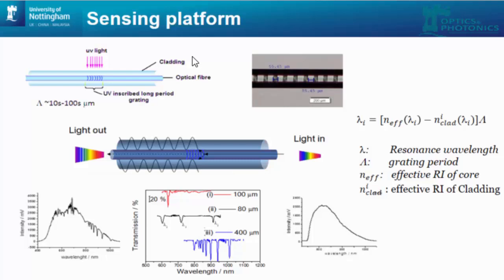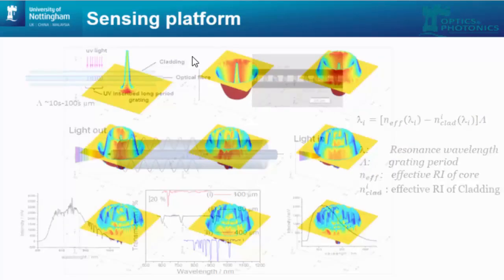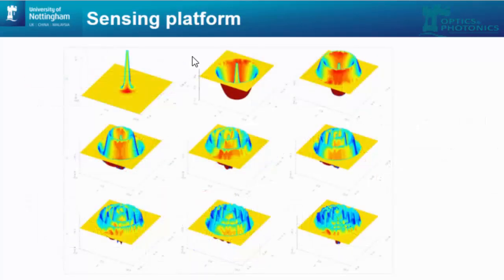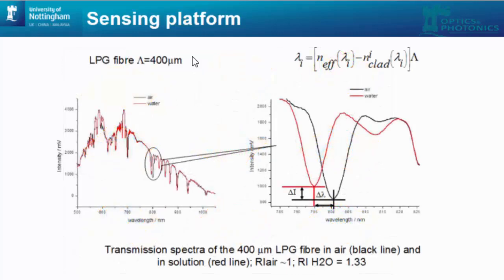So what it does to the transmission spectrum: if you put a broad transmission spectrum into an optical fiber that has a long period grating, at the end of it you will have attenuation bands, and the position of these attenuation bands depends on the grating period, so the distance between two adjacent planes, the effective refractive index of the core mode, and the effective refractive indices of the cladding modes. To illustrate this, in the fundamental core mode you have light only inside the core, no light in the cladding. If you inscribe a grating inside the optical fiber, you start to couple these modes into the cladding. So how can we make sense out of it?